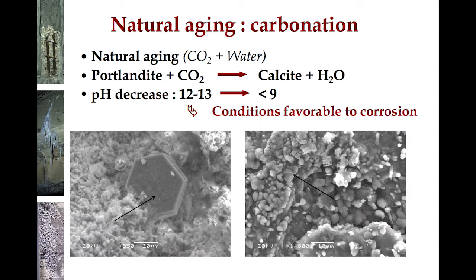So, second decay mechanism, the carbonation. This is a natural aging because we have an interaction between the concrete and CO2 and water. The portlandite, which is a major constituent of concrete, reacts with CO2 to give calcite plus water. So you can see here, it's a scanning electron microscopy picture, portlandite crystal, and formation of calcite crystal. So during this reaction, we have a pH decrease from 12-13 to a pH value lower than 9, and these conditions are favorable to corrosion.